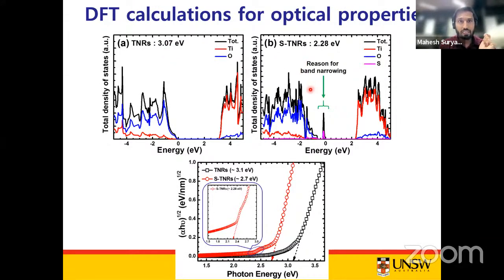Whereas the calculated DOS of the sulfur-doped TiO2 nanorod arrays reveal that the S 3p states are partially localized when the sulfur is incorporated in the TiO2 lattice. So what do these S 3p states do? Actually, these partially localized S 3p states can contribute to the formation of the valence band, which leads to the shifting of the valence band edge upwards, resulting in a narrow band gap energy of about 2.2 electron volt for sulfur-doped TiO2 nanorods, in comparison to 3.1 electron volt for pristine TiO2 nanorods.